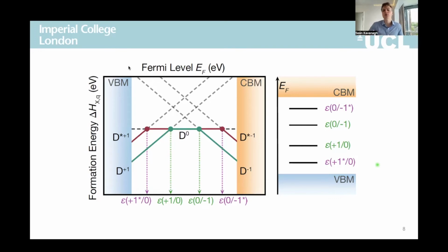So conventionally, it has been taken that charge transition levels close to a band edge will yield fast capture of that charge carrier. So for example, fast electron capture for levels near the conduction band minimum, but slow capture for the carrier from the far edge, so for hole capture. This is the conventional rationale behind deep defect levels near the mid-gap region being the most likely to be efficient recombination centers by balancing moderate hole capture and moderate electron capture to yield overall fast recombination.